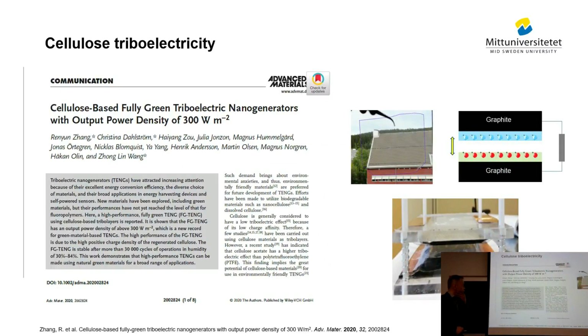And some years ago we did this. We didn't think that we would succeed with getting this high performance from cellulose. We did a whole green cellulose graphite TENG. We had graphite as electrodes and different kinds of cellulose together in the tribo layers. So one of our own cellulose and one commercial cellophane was put together. And we got an astonishing result, we didn't believe it ourselves, so we needed to redo this several times at different labs. We got 300 watts per square meter as a power output.